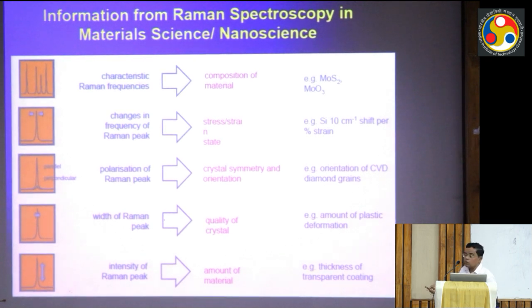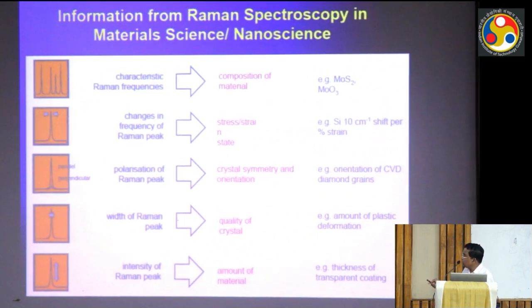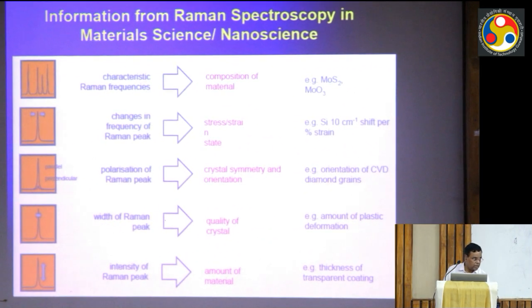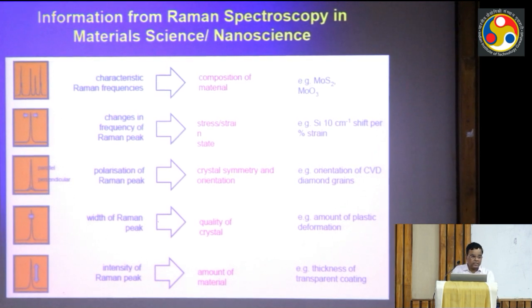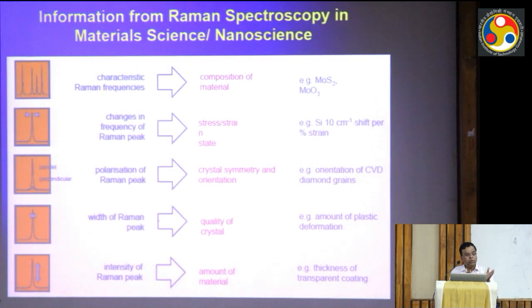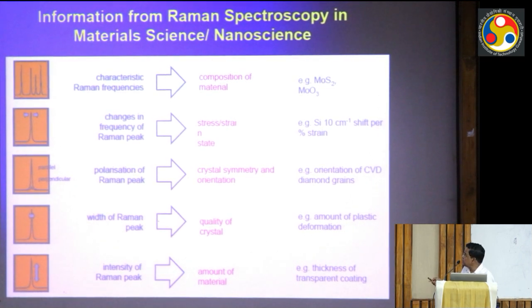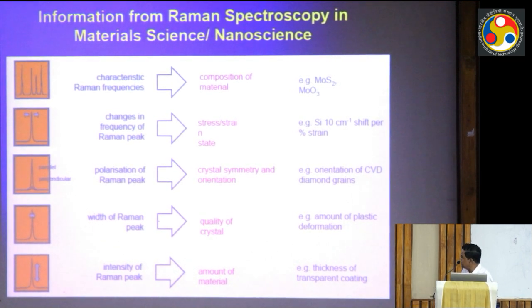So silicon has a peak at, say, 520 centimeter inverse in Raman. But if you study silicon, your own made sample through some deposition technique, and you see a peak shifted, then the change in frequency corresponds to strain or stress in the crystal. So if it is compressive strain, then the peak will shift towards the right, higher wave number. If it is tensile strain, it will go to the opposite side.